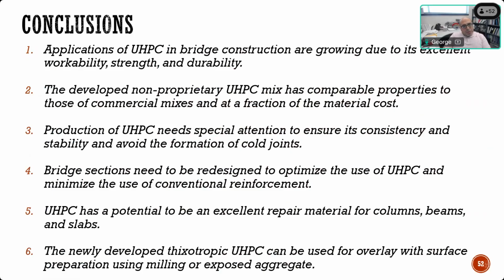If you use UHPC for a bridge component, the sections need to be redesigned. So you don't use it for exactly the same section used for conventional concrete. Whether it's a girder, a deck panel, or a pile, it needs to be redesigned to take advantage of the UHPC and the elimination or minimization of conventional reinforcement. For repair, it's an excellent repair material for beams, columns, and slabs, in shear, flexure, and axial. And we have seen that in all the examples we made in the lab and tested.